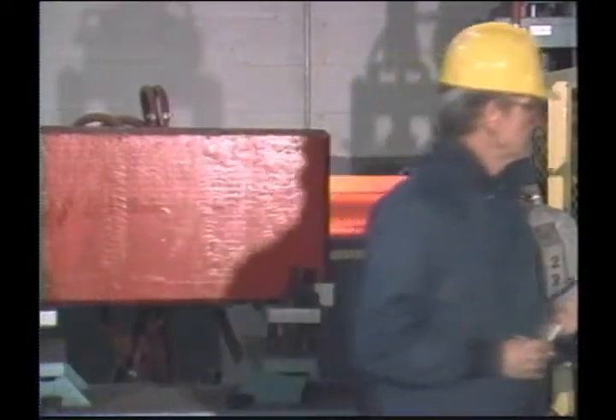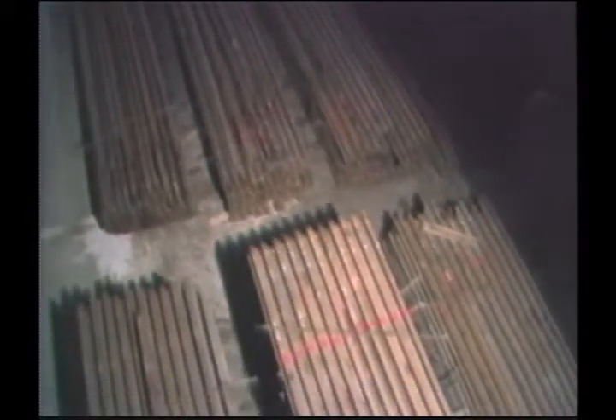The process involves heat-treating carbon and low-alloy rails to standard or deep hardness patterns, resulting in a fine pearlite grain structure with highly desirable compressive residual stresses in the rail web. When new or used rail strings are processed, a significant benefit of the Permatrack process is that the compressive stress continues right through the weld zone.